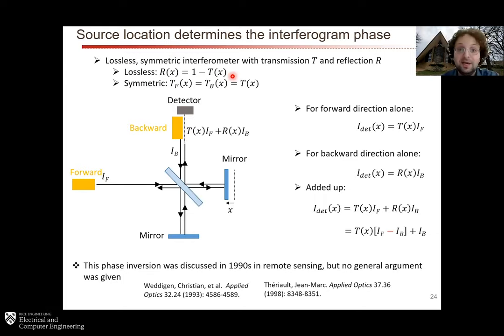that the interferometer is lossless and that it's also symmetric, which means that the transmission through the interferometer is the same in one direction as in the other direction, you can simply do some incoherent addition of the fields: the forward field, the backward field reflected, the forward field transmitted, and you find that there's actually a negative sign over here, which means that your total signal on the detector is going to be close to zero when the forward source and backward source have